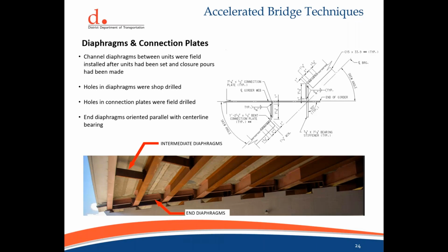The image on the bottom is a completed installation picture that shows the intermediate diaphragms, which were installed normal to the girders, and the end diaphragms were installed along the skew. The skew diaphragms were installed using a bent connection plate, as you can see on the detail on the right. The bent connection plate had to be fabricated to the skew of the bearing lines. So the as-built survey and comparing with the as-built skews were very important to make sure that the connection plate was installed correctly and that the channel diaphragms were going to fit up correctly.